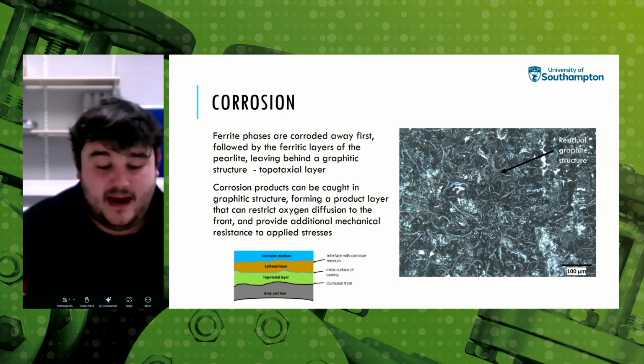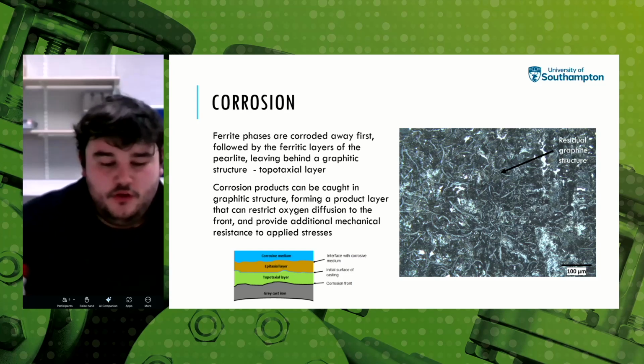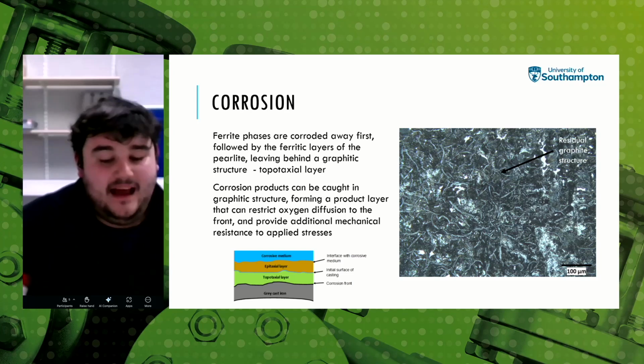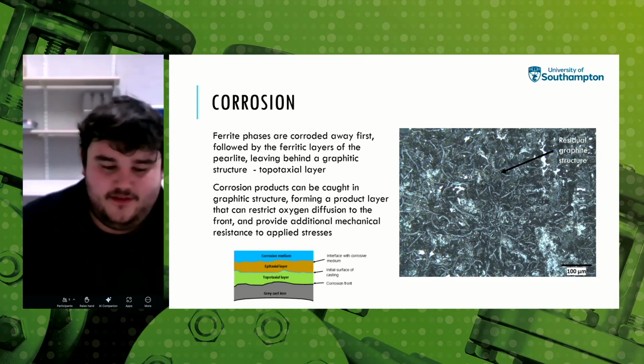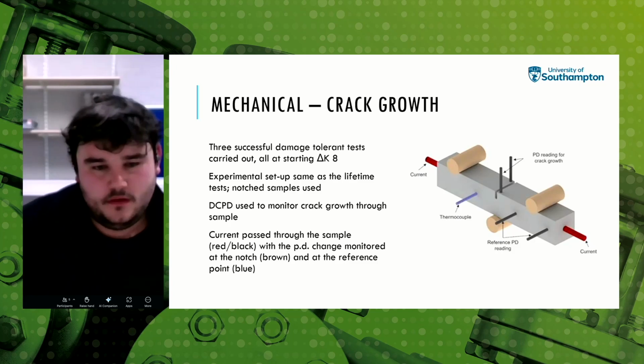As time goes on, these layers further compact and dry out and become denser. They effectively act as a barrier, like painting a pipeline, between the remaining material of the pipeline and the electrolyte and the oxygen necessary to sustain the galvanic reaction on the pipeline surface. Go to the next slide, please.